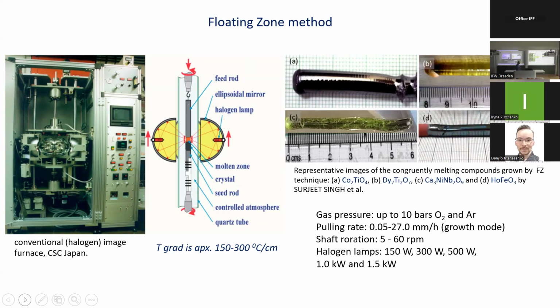These materials were grown in the group headed by Surjit Singh from India, and they give the first impression of crystal size and quality. Here you could see very typical technical specifications for all image furnaces. Normally we could use gas pressure, oxygen or argon, up to 10 bars, pulling rate, shaft rotation, and there is a whole set of halogen lamps from 150 watts up to 1.5 kilowatts. And a halogen lamp produces a very high temperature gradient on the edges of the hot zone, up to 300 degrees per centimeter.